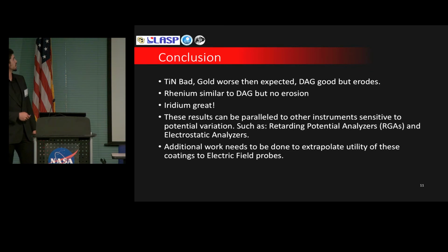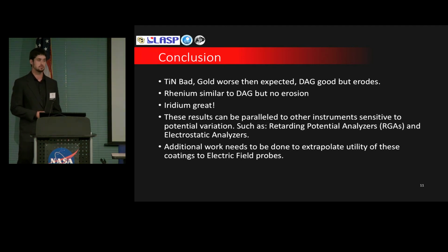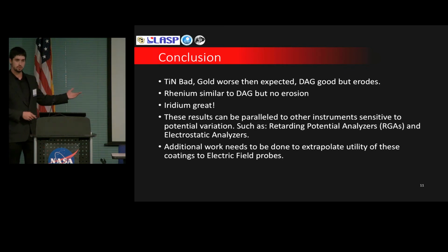So in conclusion, titanium nitride was, frankly, pretty bad as a coating for a mission that was intended to go to an oxygen-rich space environment. Gold was worse than expected. DAG was surprisingly good, but does erode over time. Rhenium had similar results to DAG, but didn't have the negative effect of eroding over time and having a lifetime. Iridium did great.